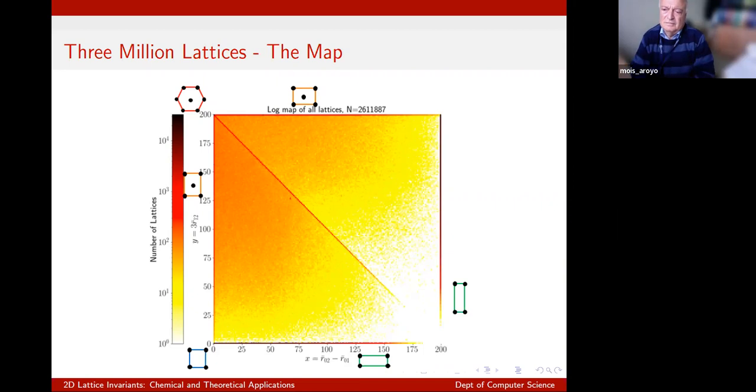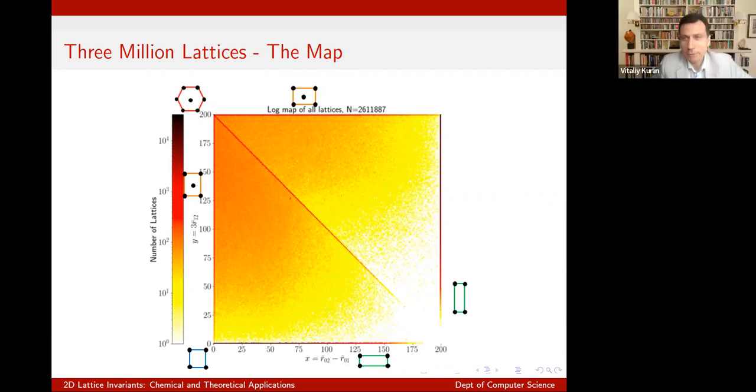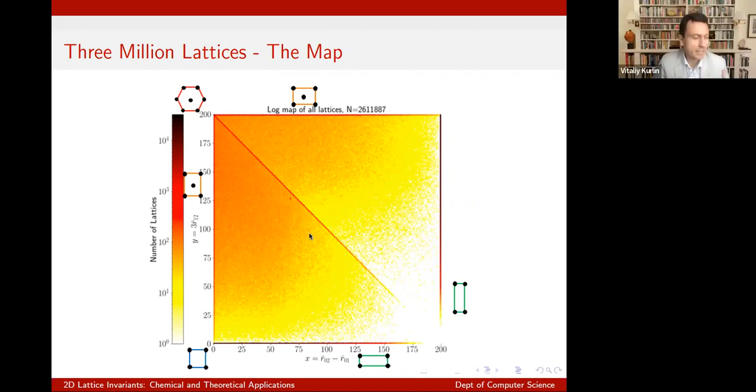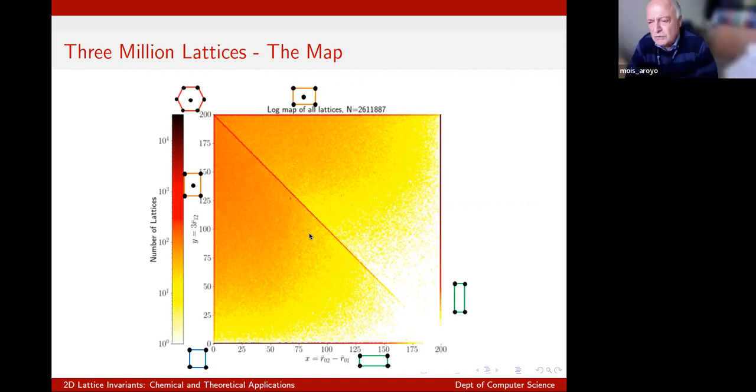Yes, Matt is absolutely correct. Even if we take randomly chosen lattices, three two-dimensional lattices from one real crystal, and if our initial crystal has, for example, a primitive orthorhombic cell, then as a result we get three rectangular lattices. So you see, high symmetry is even more exposed as a result. We have a more skewed distribution towards high symmetry lattices for that reason. This is what I was meaning.